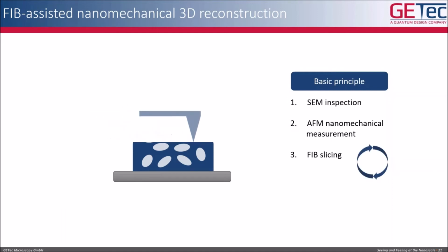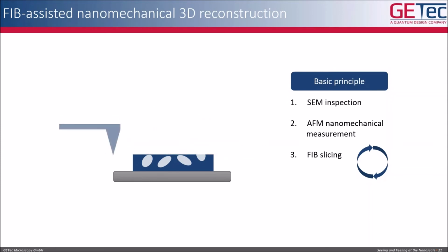So do the mechanical measurement with the AFM, use the ion beam to slice away, mechanical measurements, and the ion beam slicing. And in this way, you can really get a 3D reconstruction of the mechanical properties of your sample.